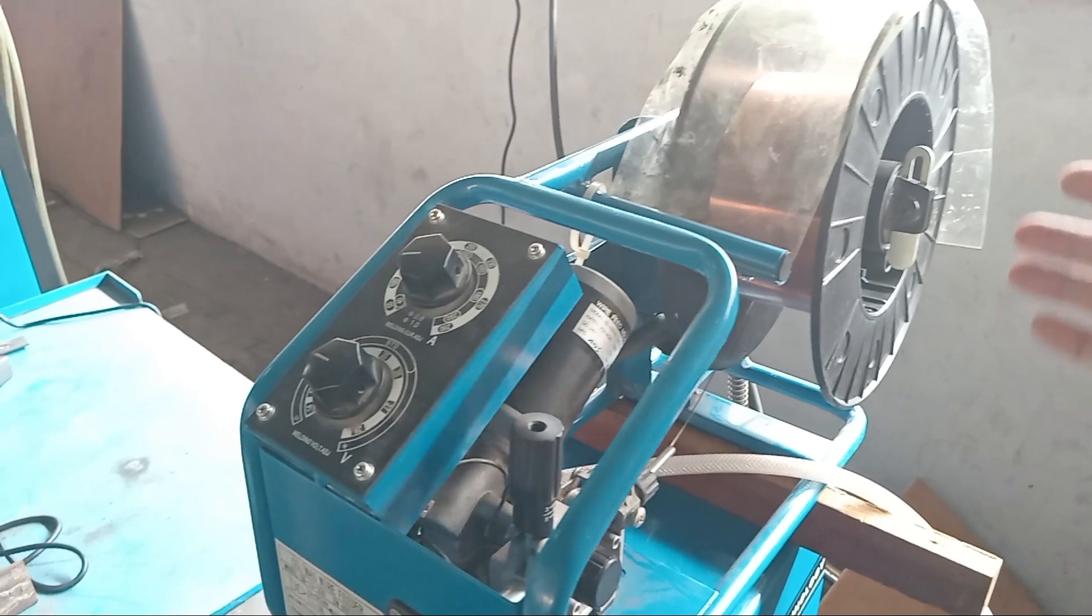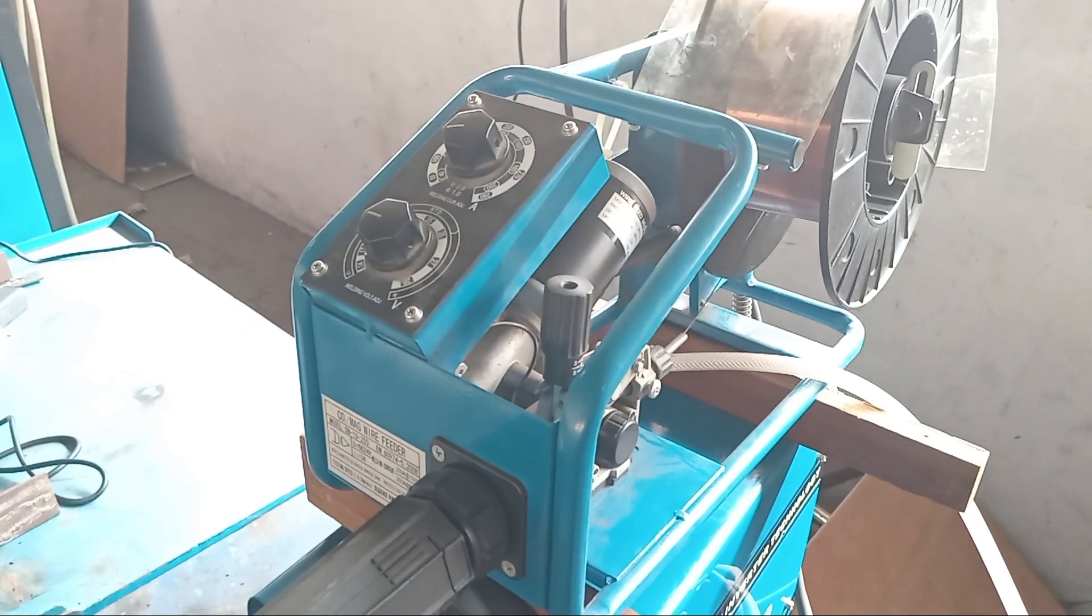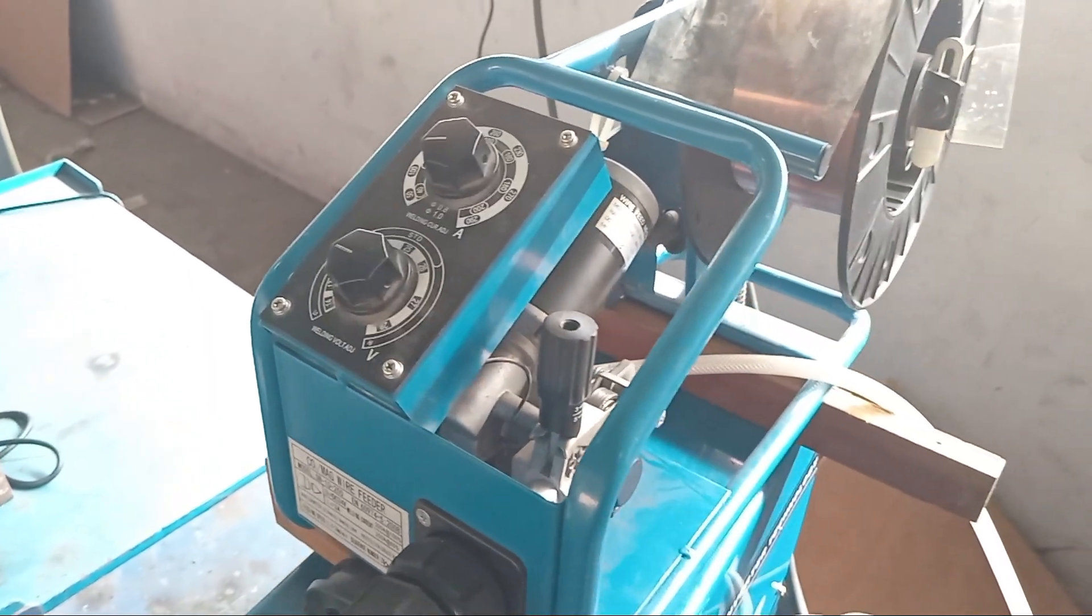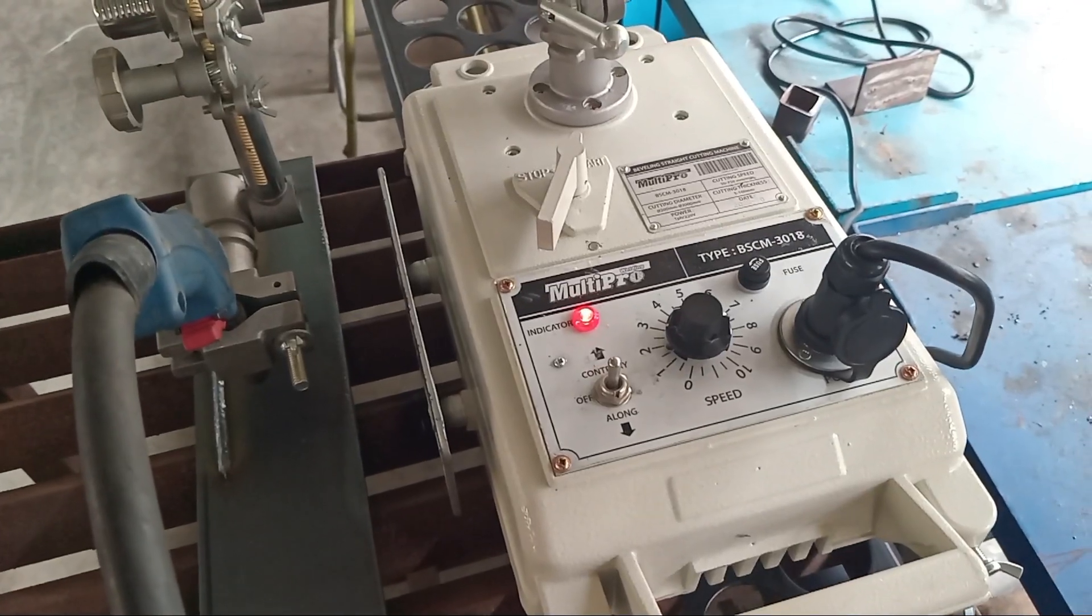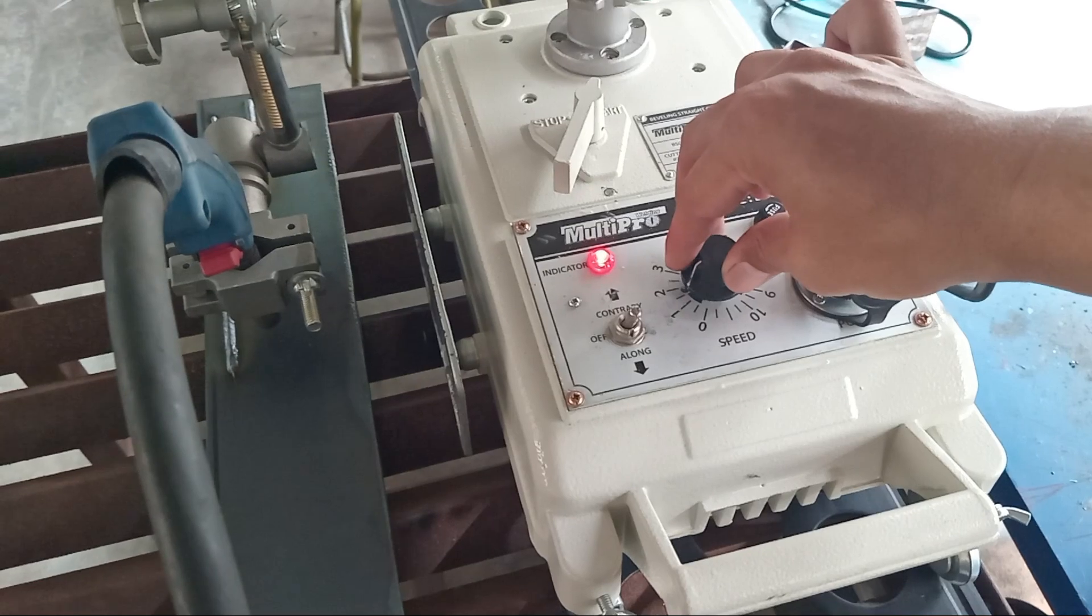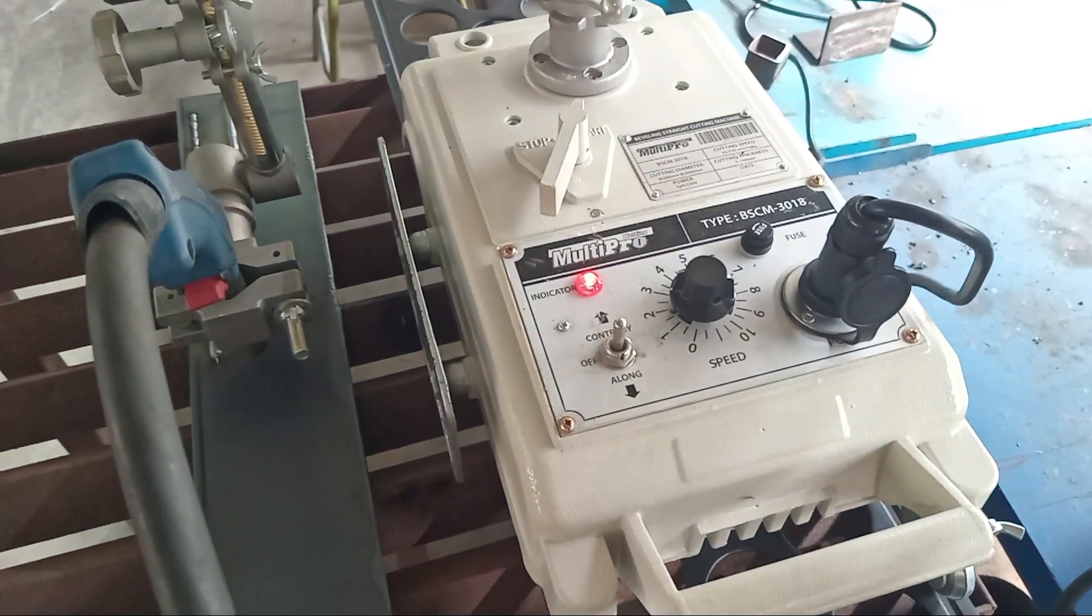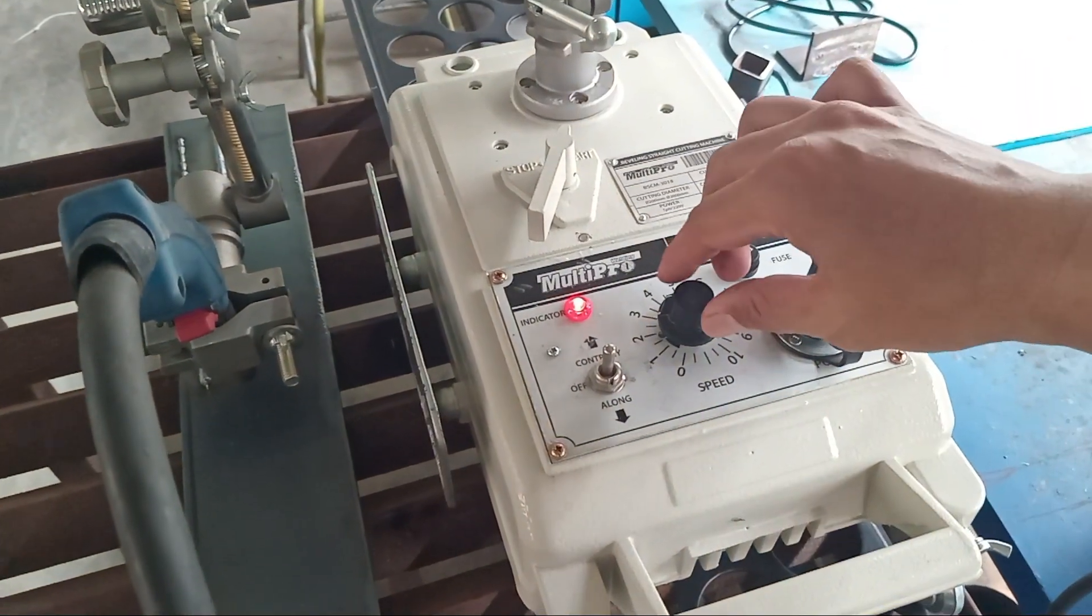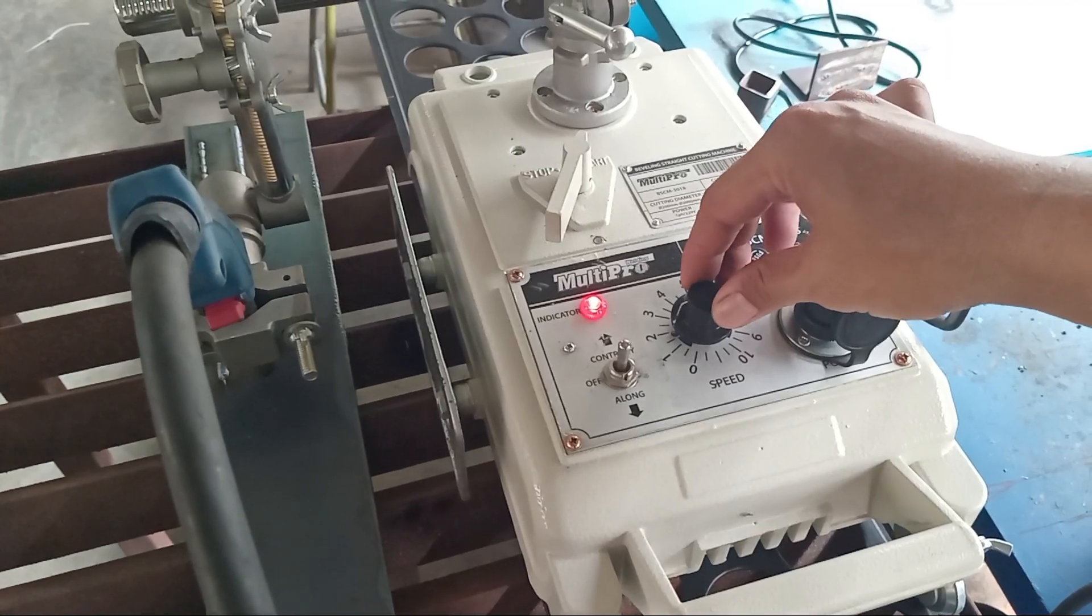The welding wire is 0.8mm according to the plate that will be welded. These are the volt and ampere settings. Then the settings for the BSCM here - this is the speed or movement of the motor, so how fast the motor speed is. For high ampere or MIG welding, it's between one, two, and three here for the speed. If it's too fast, the welding result will be broken, not good.